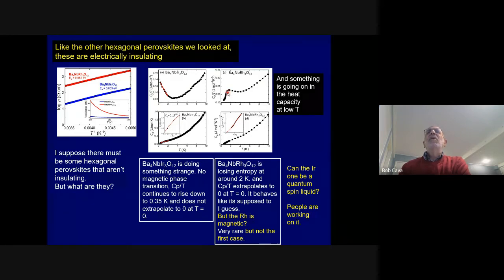The heat capacity is a good way to look at these things, because if you have magnetic ordering, you go from a disordered magnetic state to an ordered magnetic state, and therefore you lose entropy. So the heat capacity is a good way to look at the entropy loss. If you see a peak in the heat capacity, that means you lost entropy. So the system magnetically ordered for the rhodium case, but in the iridium case, it didn't.